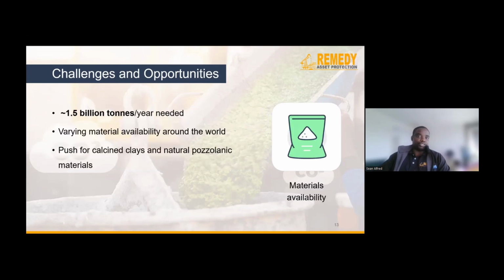Now, if we look at materials availability, currently we have about 300 million tons per year of traditional SCMs that are available globally. And when I say traditional SCMs, I'm talking about your fly ashes, your slags, those industry byproducts. But to achieve a 50% cement replacement across the industry within our normal concrete production, we're going to need about 1.5 billion tons per year. So you can already see the mismatch and the gap between available SCM stocks and what we actually need if we were to change the way we design our concrete across the board.